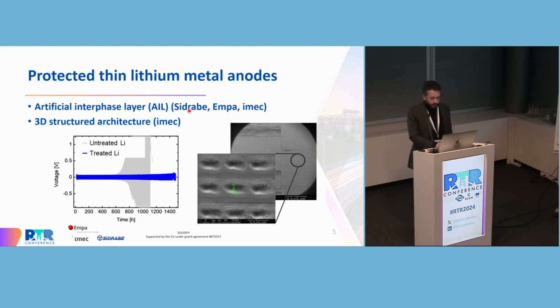One of our partners has a high efficiency PVD process for depositing lithium at high rate, and we could get a lithium electrode with an overall thickness, including a current collector, of 30 microns. This electrode is then protected or optimized by forming an artificial interlayer, and in this regard we have been working together with EMPA on protecting the lithium current collector, and this is reflected as an improvement in terms of cycle life of the cell.